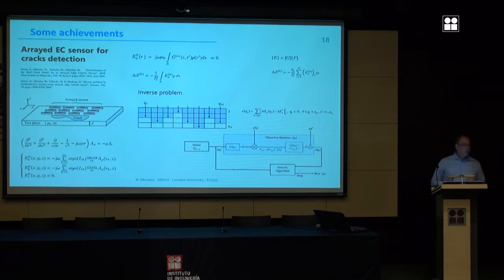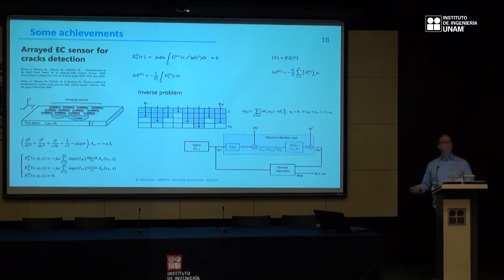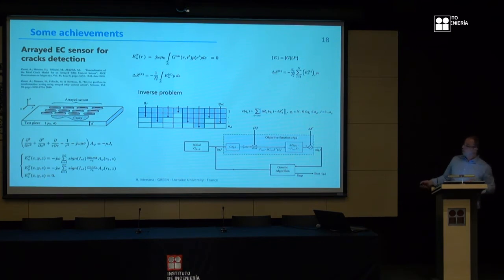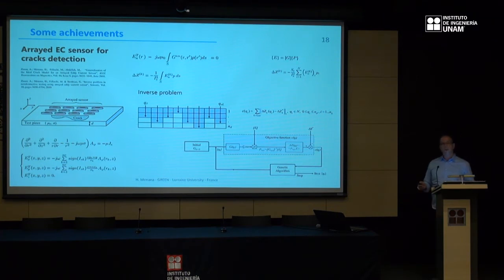In this work, we have considered an array eddy current sensor to characterize flaws, cracks in conductive materials. It's a 3D problem, very complicated to model in 3D. So we developed a modeling approach to avoid the 3D approach. We did just an axisymmetric modeling of a coil above a conductive plate, and then we reconstituted all the source fields created by the coils by moving the coordinates of the coil. So we have the source field created by all the coils in the tested material.